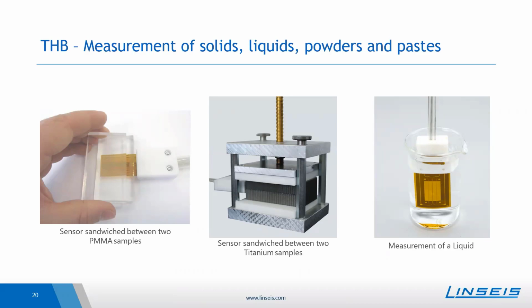Here one can use a trick as well. One can apply a very thin layer of thermal paste or a copper paste on top of the sample surface so that it's smoothened, and then one can bring in the sensor. And of course, with a rougher sample surface, it's better to use a lower contact pressure to compress the configuration.